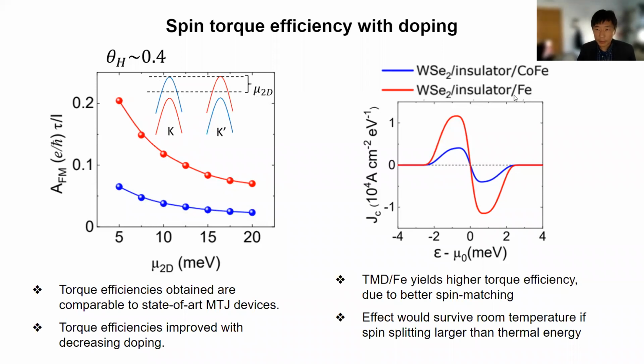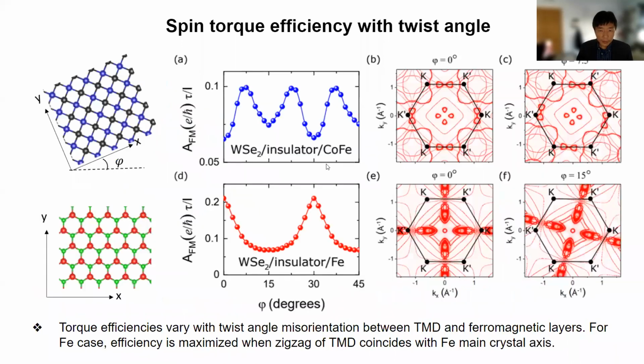And then we begin to look at possible ways to enhance that performance. So we look at different types of magnetic materials, because we see that the matching between the spin states is very sensitive to the band structure. We also look at other magnetic materials like iron, and we observe that indeed for the case of iron, you get an enhancement compared to the case of cobalt iron. And the performance is also sensitive to the orientation between the TMD and the magnetic layer because of the matching between the spin states. And here what you see is the figure of merit as a function of this orientation angle.